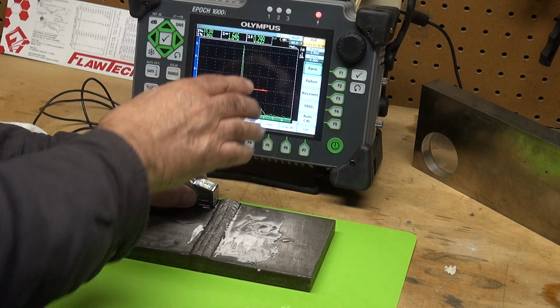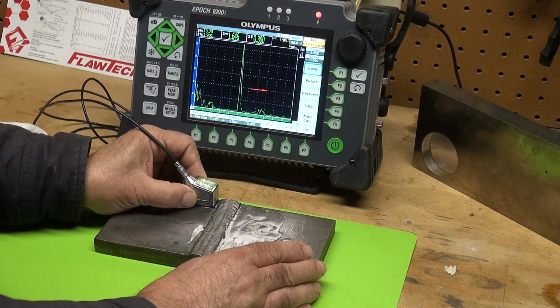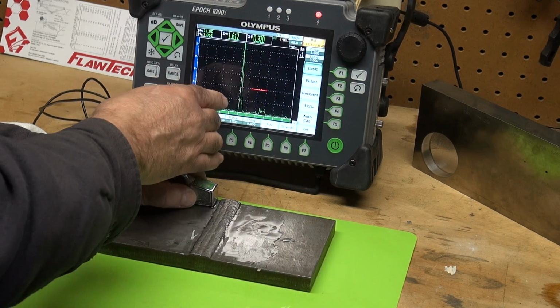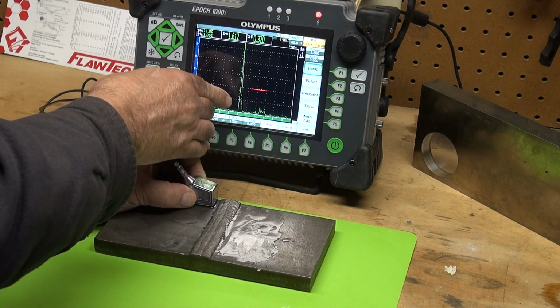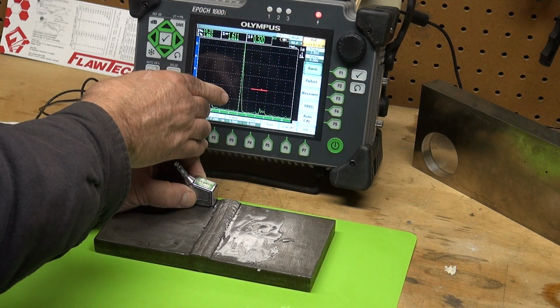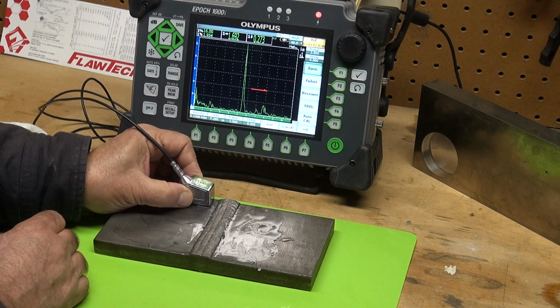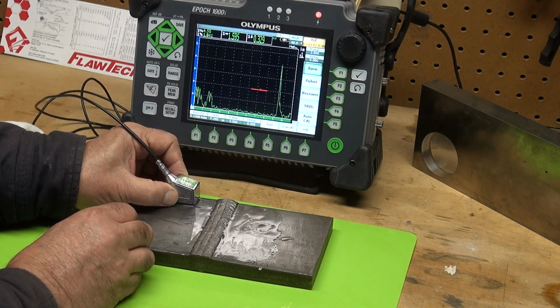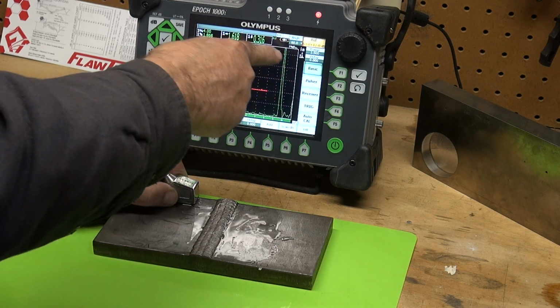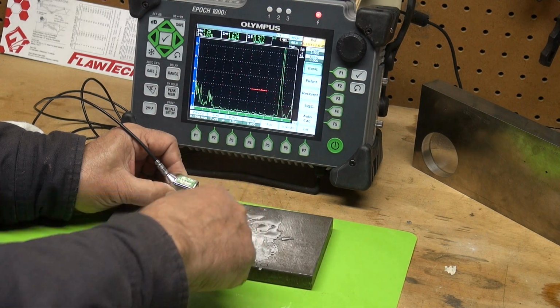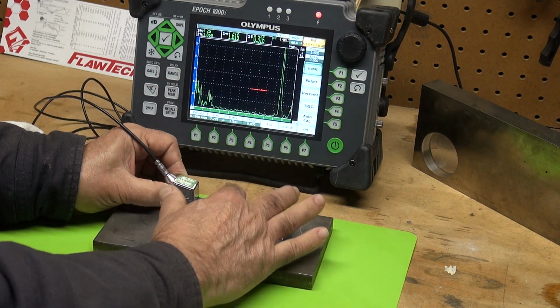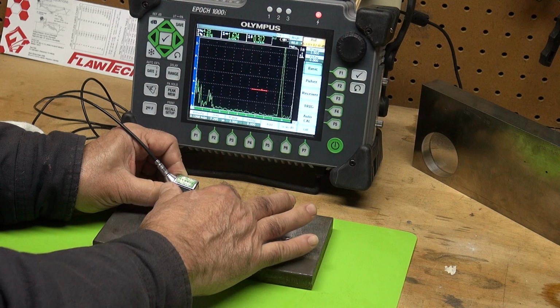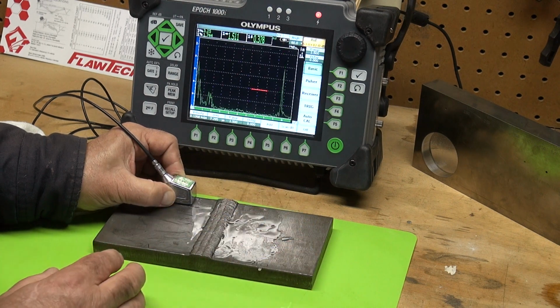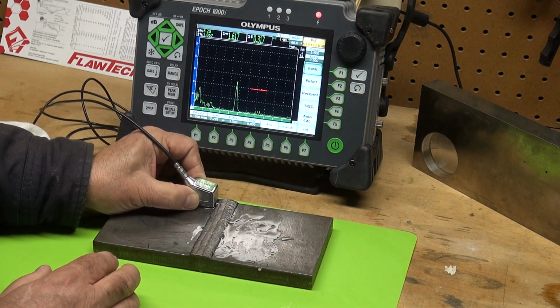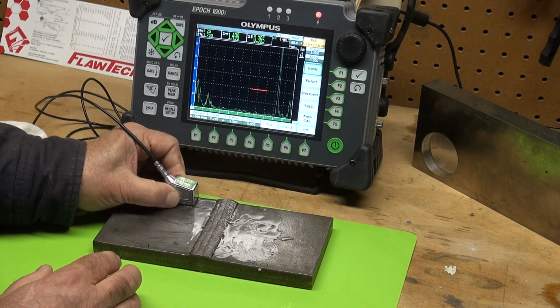Looking at this weld, this is a good area of the weld, defect free, right there about mid screen. That is the very bottom of the weld. That's my root signal. That's geometry. As I pull back, we'll see that signal jump up. It is my toe of the weld. Geometry. And right here, I can maybe finger dampen it. You can see it a little bit. But those are normal geometry signals that you'll see.